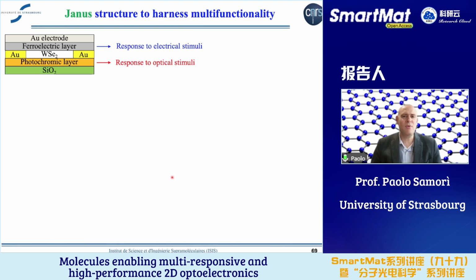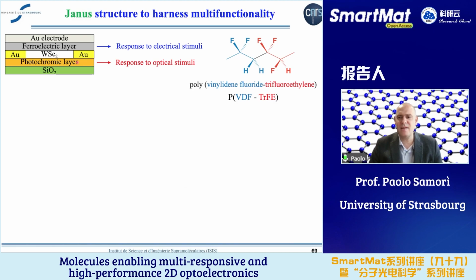And the idea is that we place the photochromic layer on the bottom of the tungsten diselenide, therefore in between the tungsten diselenide and the silicon dioxide surface. And on the top, we use a ferroelectric layer. And so we use an organic ferroelectric material that people in organic electronics know very, very well. This has been thoroughly used in organic electronics for fabricating ferroelectric field effect transistors.